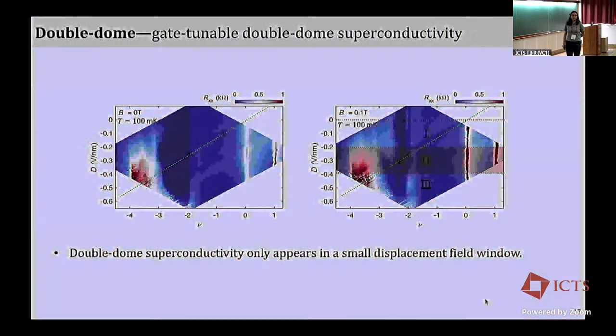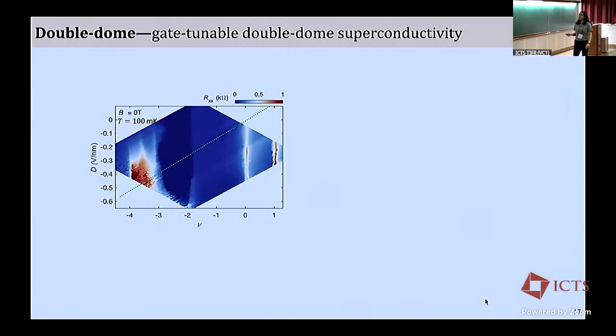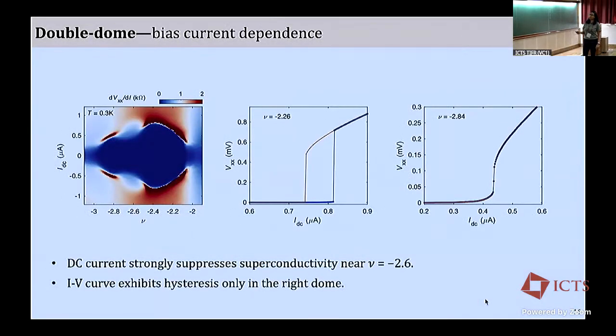So basically, what happens for the hysteresis part is that if you smoothly go, I did put this 2D plot here. So in here you have the hysteresis, here you don't have it at all, and in between it kind of goes through this. After 2.4, we stop seeing the hysteresis. And of course, depending on the quality of the sample, how good a hysteresis you see, this for sure. I have another device where the hysteresis was not as wide, but it was there. But it always stops here.